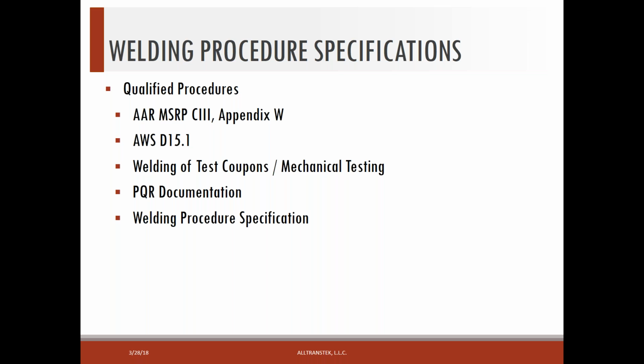So once we identify whether we can use a pre-qualified procedure, if we can, then we can eliminate the mechanical testing. If we can't use a pre-qualified procedure, then of course we have to first weld test coupons that will be mechanically tested, and that will lead to our procedure qualification record, the results of the mechanical tests. And once we have that, then we can establish our welding procedure specification.